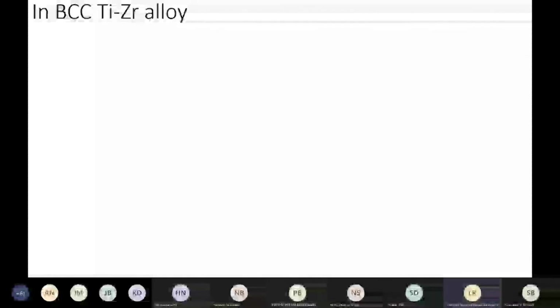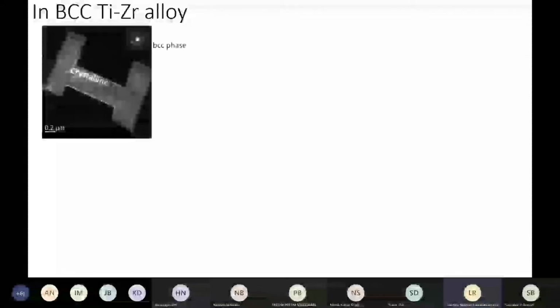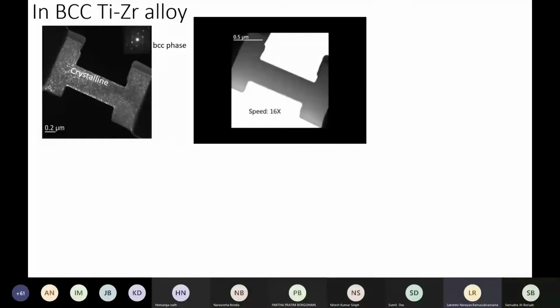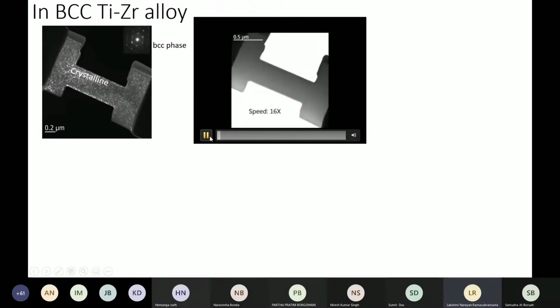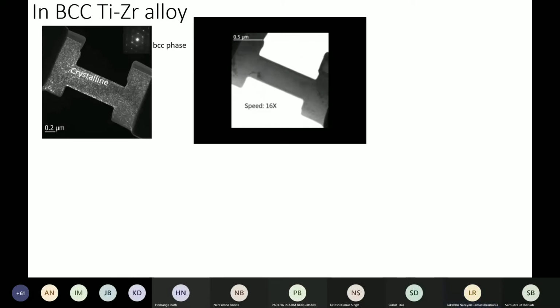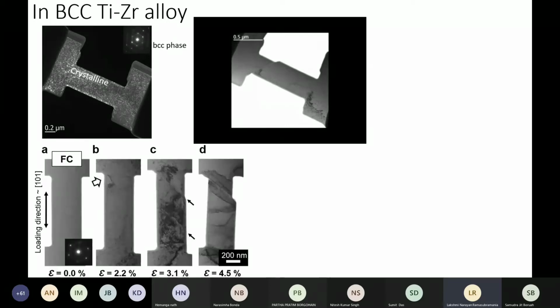So now if I look at BCC materials, again a similar thing was observed. We are looking at a titanium zirconium alloy, and this has a BCC phase. Here is the dark field image of the same. And I'm going to show you another video. Here your tensile axis is diagonal, and you see that this sample is yielding, and then you will see the formation of an offset. Okay, and this offset grows and this sample no longer undergoes uniform elongation. Uniform elongation is necessary for a sample to exhibit ductility, and that does not happen.